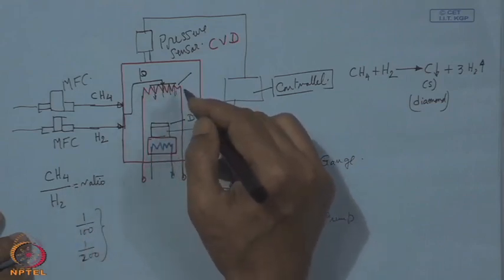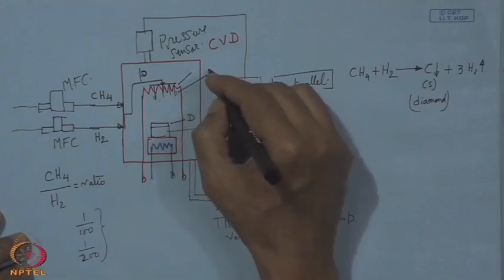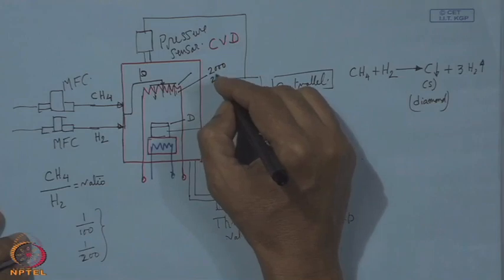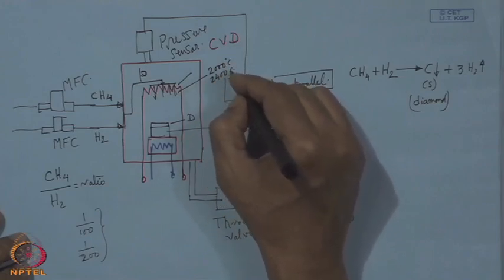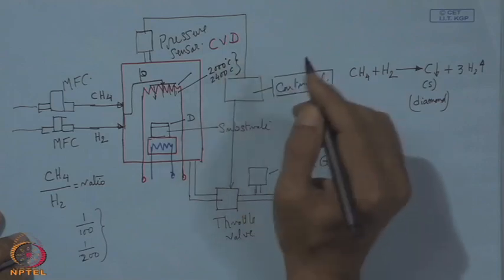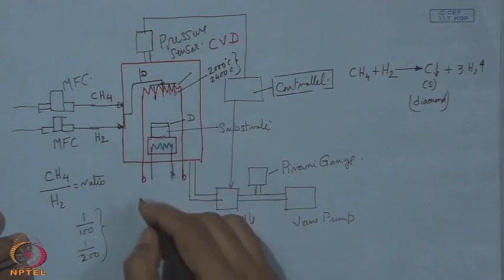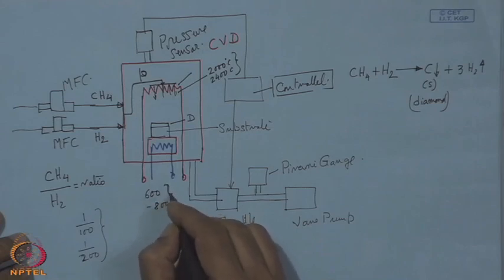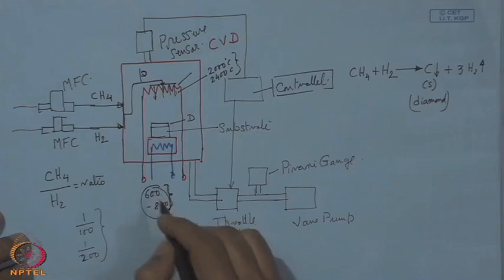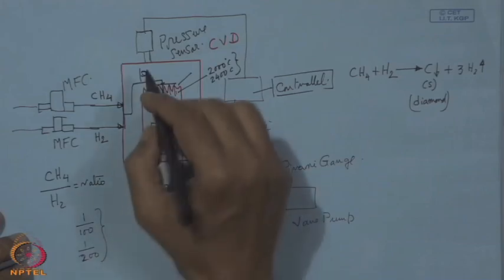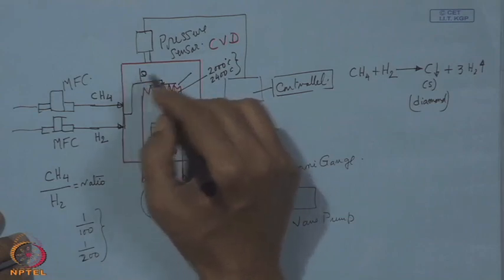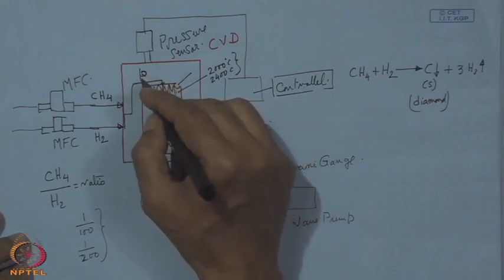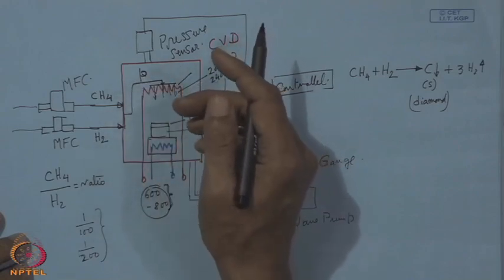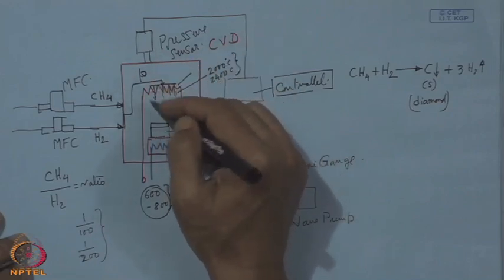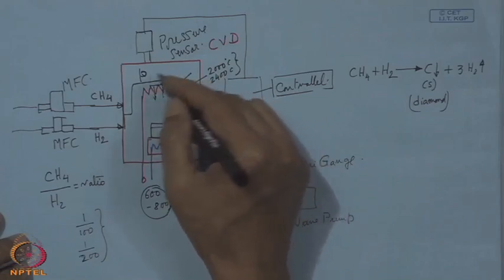Now, some indicative values which will be useful: the filament temperature is 2000 plus, and it can go up to 2400 degrees. This is an indicative value or range. Similarly, the substrate temperature can be, say, 600 to 800. There are of course parameters or conditions which will govern the selection of the exact value. Pressure, we can have any range, but according to research publications and investigations, it is kept around 10 to 30 or 40 torr, and that is the operational range.